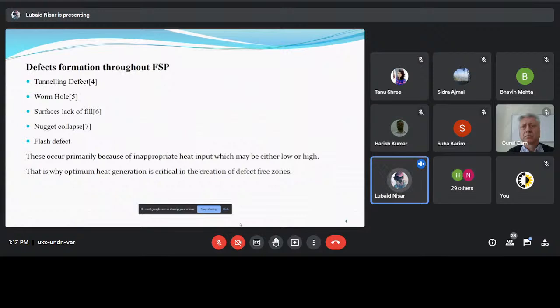Next is nugget collapse. Usually, it is found in the stir zone of the processed material. It is caused by high heat generation. The high heat generation leads to the formation of intermetallic compounds, which are hard and brittle and result in deteriorating the mechanical properties of the material, which are ductility and strength.